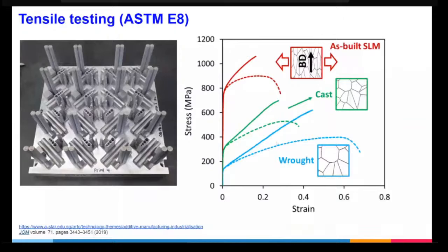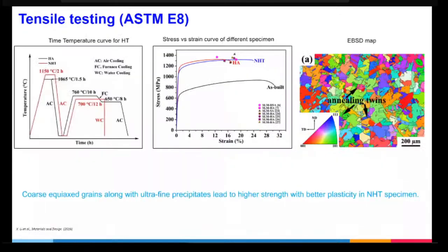cast also. You see here some of the heat treated components. It's actually tested under tensile or static loading conditions, and see as built and heat treated. So sometimes you can see the heat treated samples show a higher amount of strength, but when the strength is increased, it is normally seen that the ductility is compromised. So ductility is seen to be decreased.